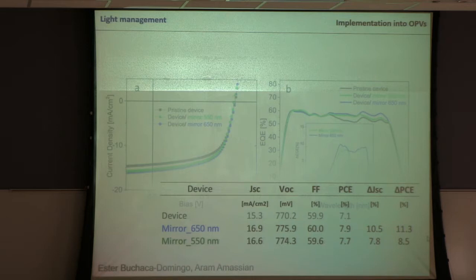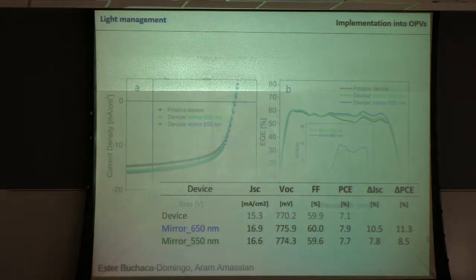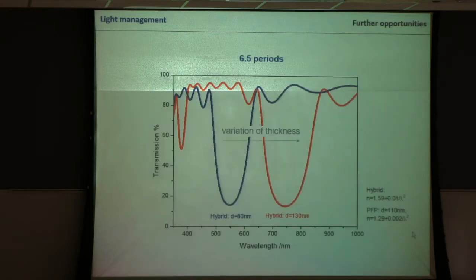So that means even now, with solar cells, nowadays we can get 13%. Most of the time, the 17 is really a tandem device. But we can increase the efficiencies, so it makes it more and more attractive to go into these types of applications. More importantly, which would work for all the solar cells, inorganic or organic, we can start to push this reflection band into the near infrared.